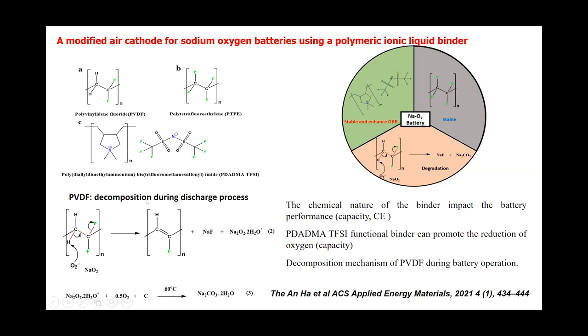I would like to highlight some key findings from my research. The first one: the chemical nature of the binder impacts the battery performance, especially capacity and coulombic efficiency, and also the PDADMA TFSI functional binder can promote the oxygen reduction, gaining in regard to the capacity. Finally, the degradation of PVDF during battery operation. We found sodium fluoride and sodium carbonate as side products, leading to the limited capacity. And another work.